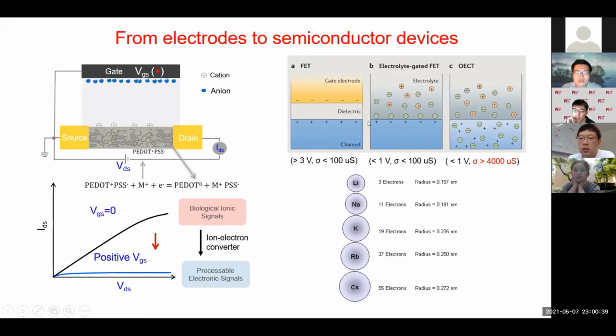In this case, since you only have the capacity to induce the conductance here on the interface, 3 nanometers or maximum 10 nanometers, it's not enough. So using conducting polymers to make it porous, that means not staying on the surface but also making them bulk, right? In this case, you have much higher sensitivity. I give you a parameter. It can be 100 or even 1,000 times higher, the sensitivity.